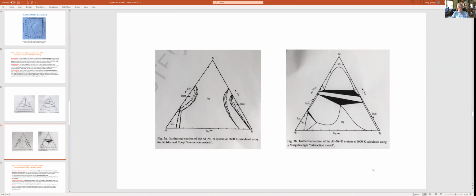Now, I don't know how many of you are familiar with the Margules and the Kohler and Toop. I don't know, do you see my cursor? If I take any point in this ternary, the Kohler equation would take a point from the axis through that composition from each of the vertices and calculate from the points of interception on the binaries, from the vertices to the binary. The Toop goes from one vertex through the chosen point, and then there is a constant composition for the element of that vertex, and the points of composition on the binaries are used to obtain the binary values.